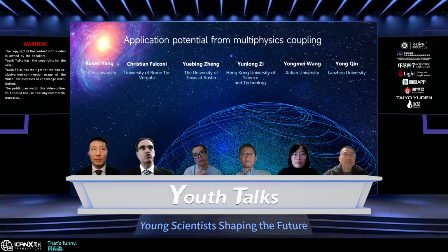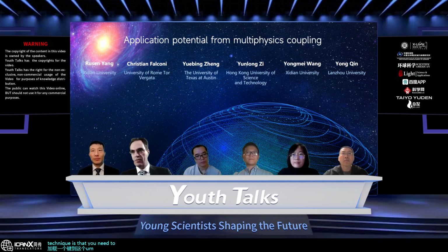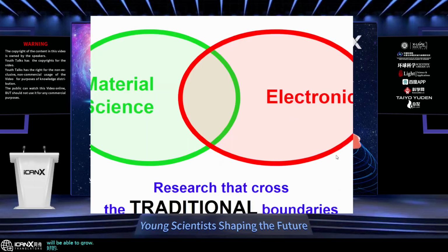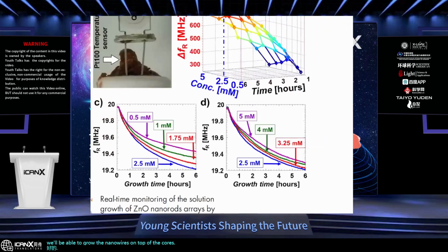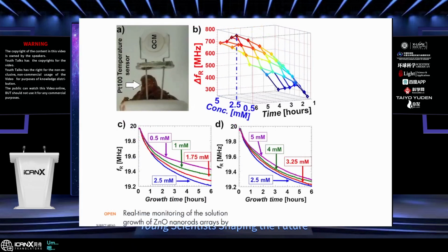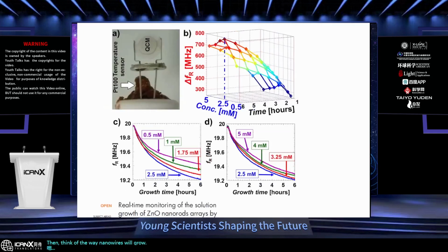So one key to this technique is that you need to be able to grow the nanowires on top of the quartz crystal resonator. And that was very simple in our case because it was just zinc oxide nanowires, and they can be easily grown on these silver electrodes. So these are the silver electrodes of the microbalance. And with a conventional wet chemical approach, you can find details in the manuscript, then zinc oxide nanowires will grow. So very simple wet chemical process.